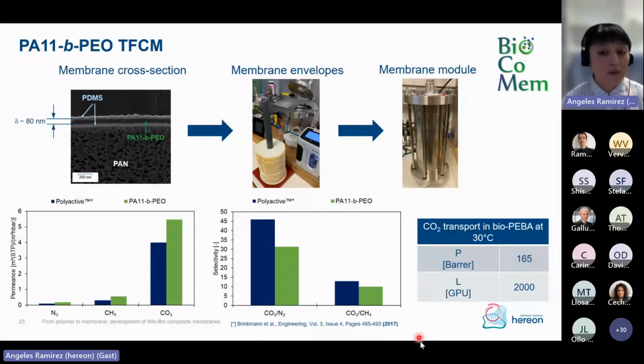And if we compare this newly developed membrane to our benchmark polyactive membrane, we see that this block copolymer is much faster than the polyactive, but it has a lower selectivity. And actually, this is not so bad because we could use this membrane for a first stage separation in the treatment of flue gas, for example, which is quite nice, as this type of membrane will imply using less membrane area for such an application.